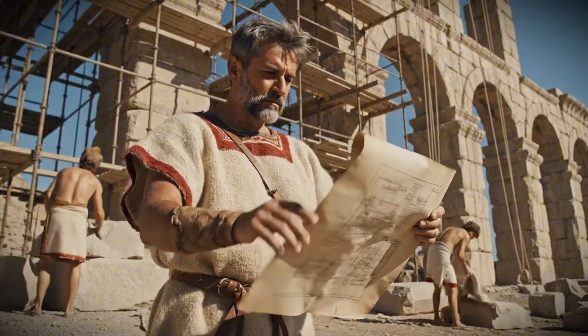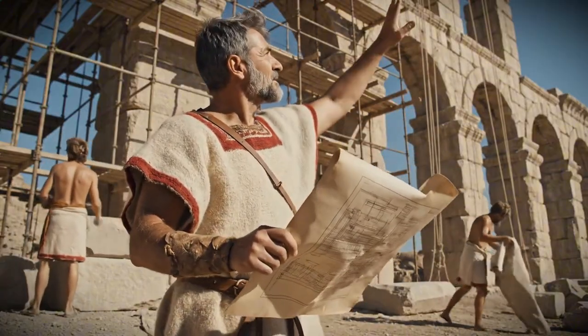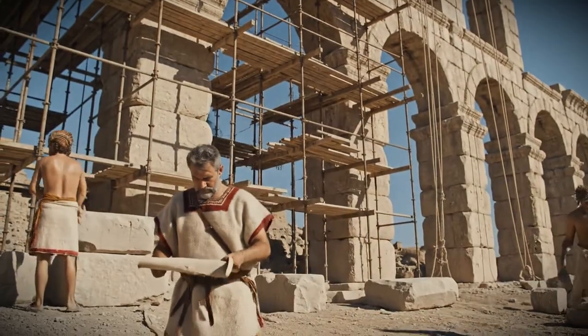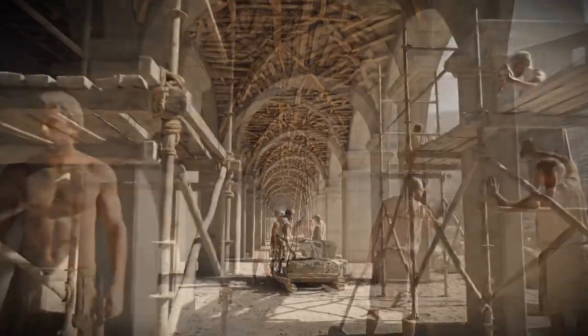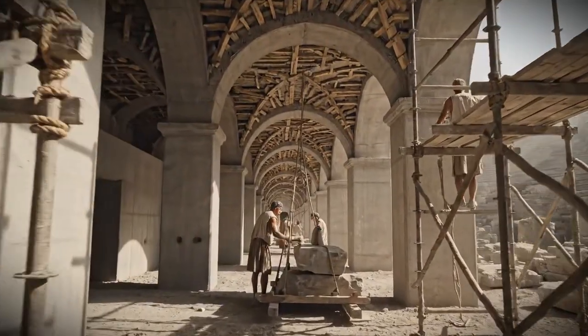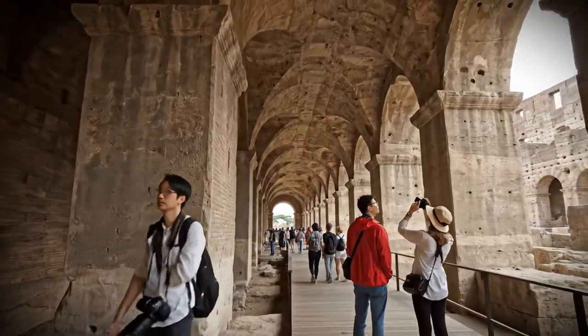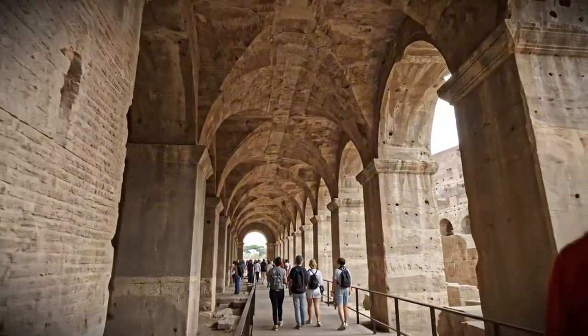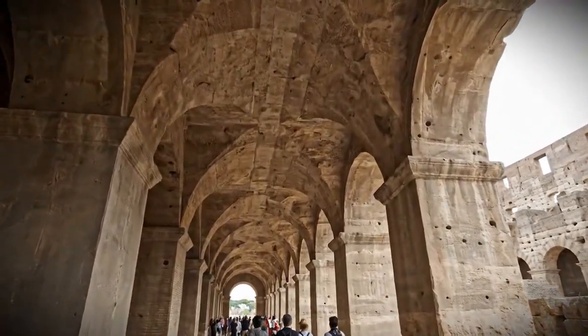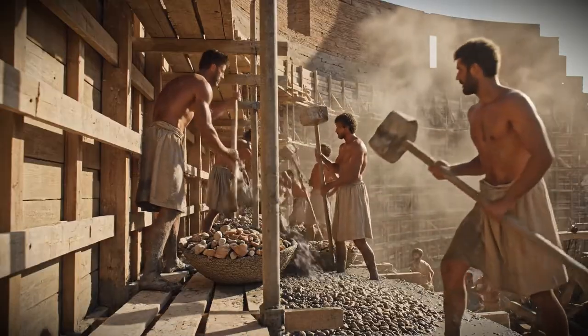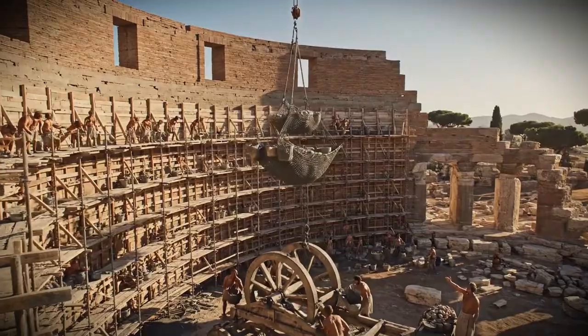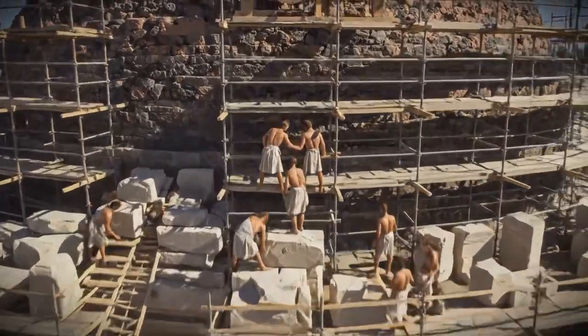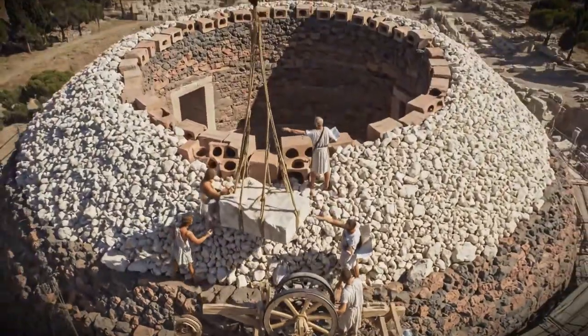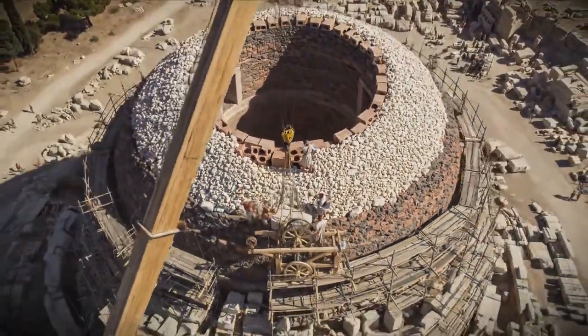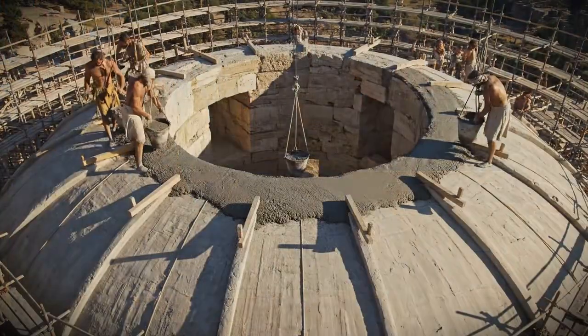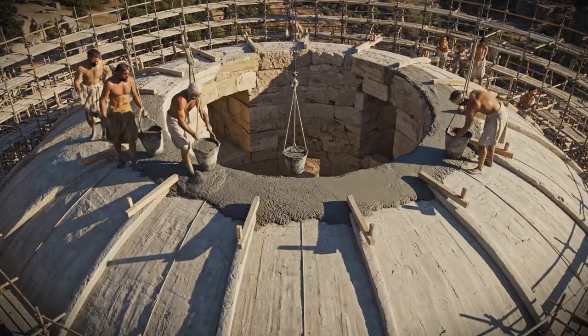But they developed an even more ingenious technique for locations where cofferdams weren't practical. They created what we might call self-setting concrete bags. Workers would fill large linen or leather sacks with a dry mixture of lime and pozzolana, seal them tightly, and lower them into position underwater using ropes and primitive cranes. "Make sure the bags are packed tight," a harbor engineer might instruct, "and position them so water can penetrate from all sides." As seawater gradually seeped through the fabric and saturated the dry mixture inside, the pozzolanic reaction would begin. The bags would slowly set and harden underwater, fusing together into a solid mass. Once enough bags had been placed and set, they'd form a stable underwater platform that could support additional construction.